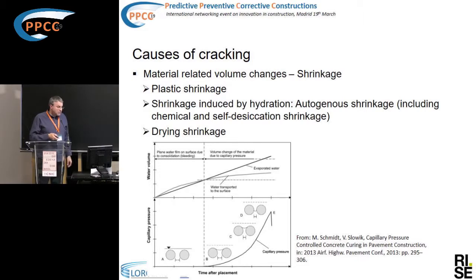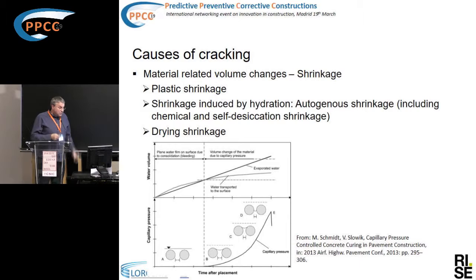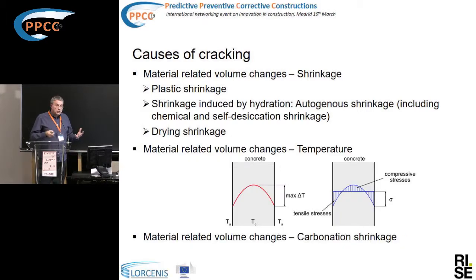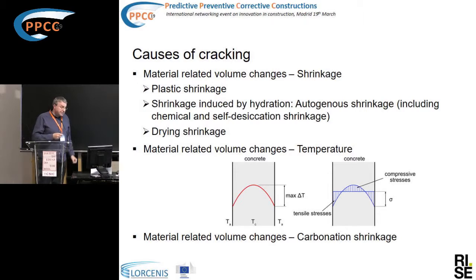Drying shrinkage, self-desiccation shrinkage, and plastic shrinkage are actually based on capillary forces or capillary stress within the pore system of the material. Further volume changes can be based on temperature. During hydration, the reaction is exothermic and will increase the temperature of the concrete. Due to temperature gradients, stresses can develop, and cracking can be caused by tensile stresses on the outside of the concrete.